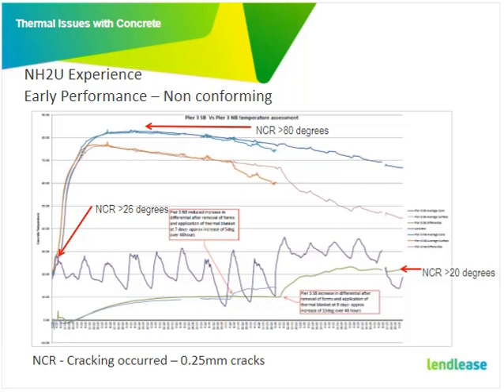That's the differential temperature. As you can see, we had the insulated forms on, and it was very well controlled. At that point we stripped the form, and one of the issues we had is we couldn't get that blanket on quickly enough due to the construction methodology. It was the first one. They had a few stuff ups where things didn't quite fit, and it took them a little longer to get it on. As you can see, the differential temperature with the outside face started to cool from the wind and other things. So that crept up, and we had a non-conforming differential temperature, and the result was some cracking.